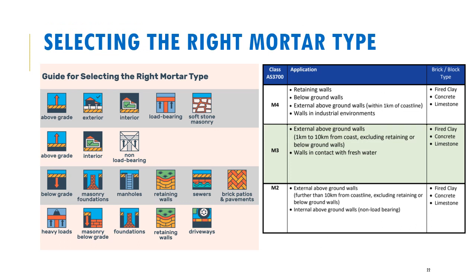There are three classes of mortar in Australia: M2, M3, and M4, and different classes have different applications. M4 mortar class is used for masonry structures adopted as retaining walls or below-ground walls. External structures that are above-ground walls would use M3 as the mortar. M2 mortars are mostly for external structures above ground walls, or even internal ones, and they have to be non-load-bearing. The table also gives you the type of masonry unit to adopt — clay, concrete, or limestone — applicable for all three mortar classes.